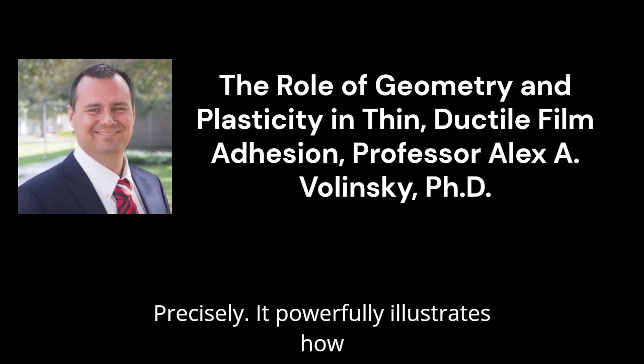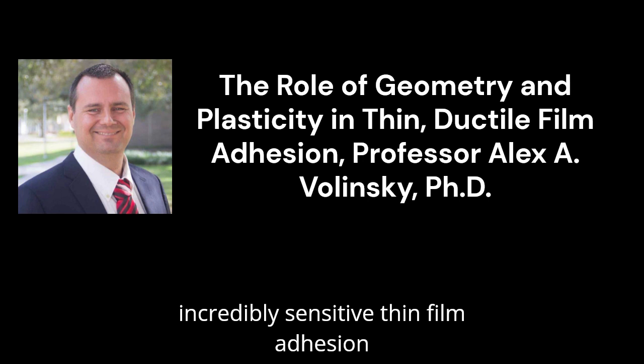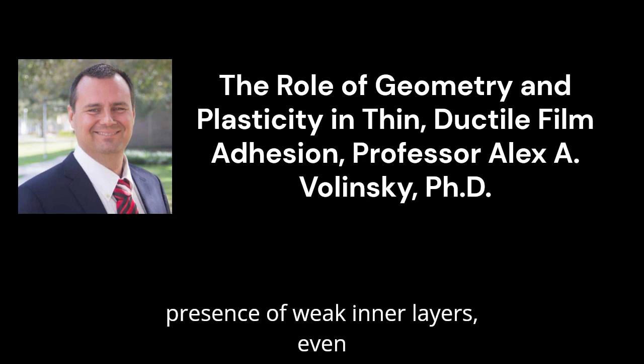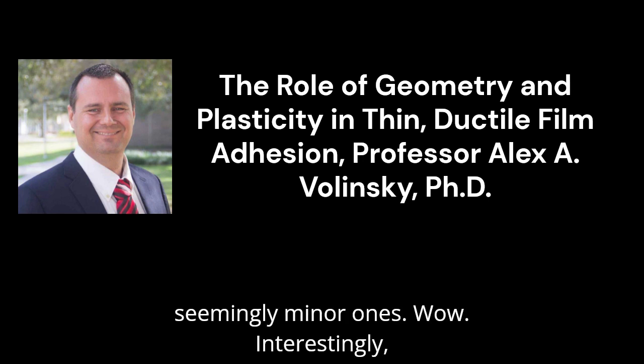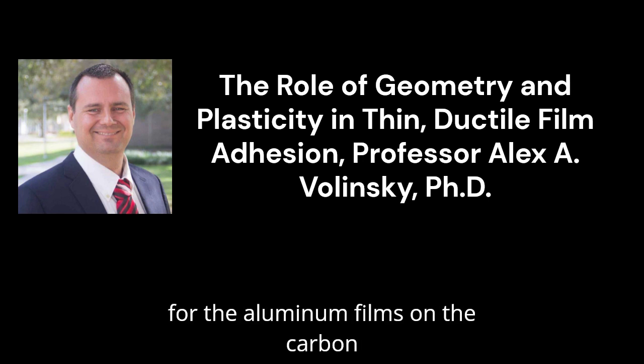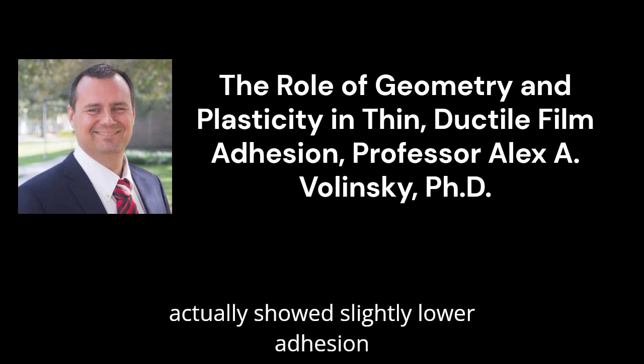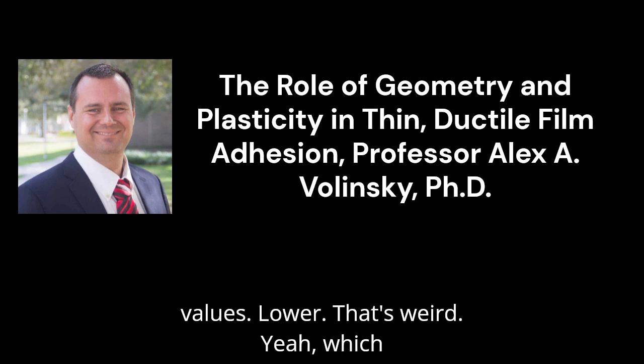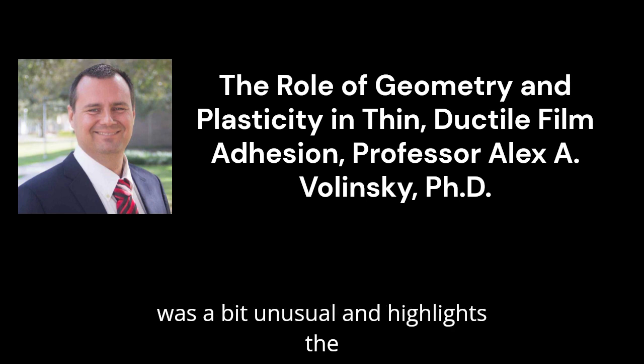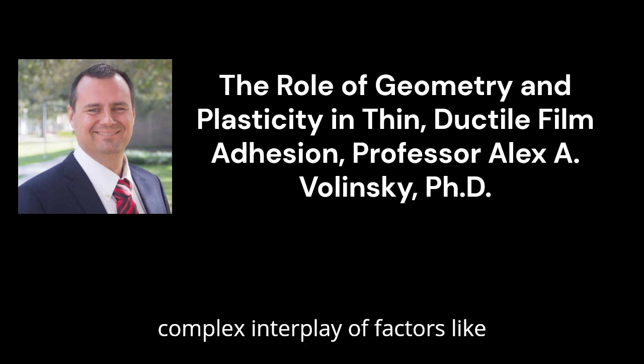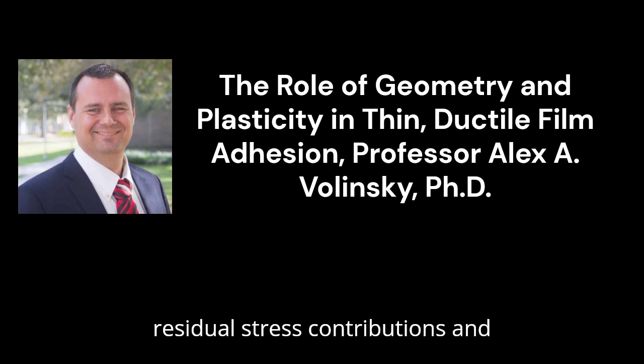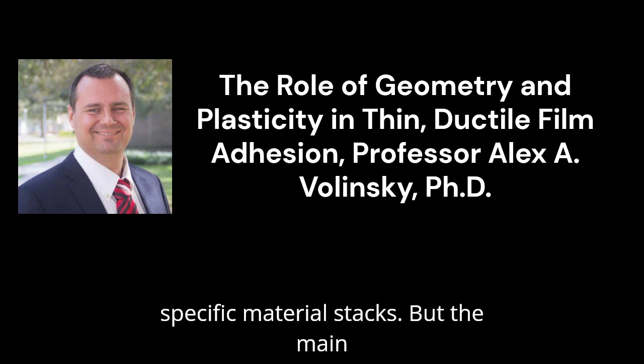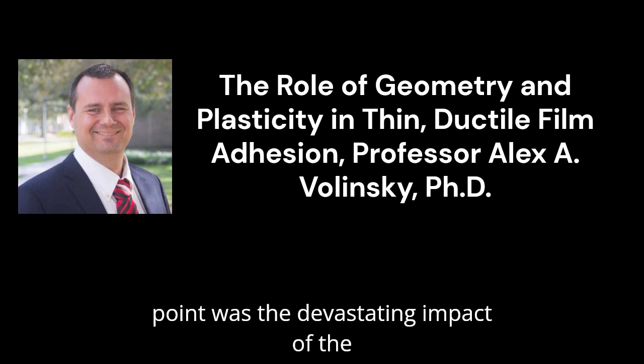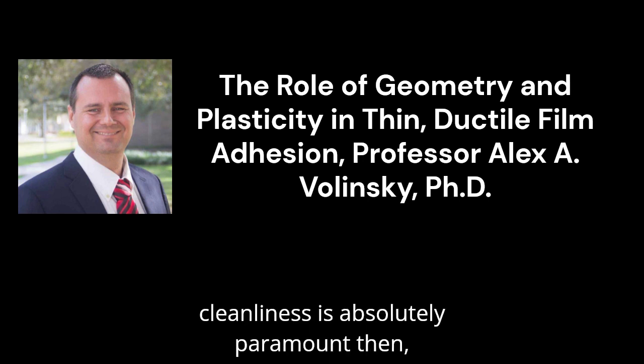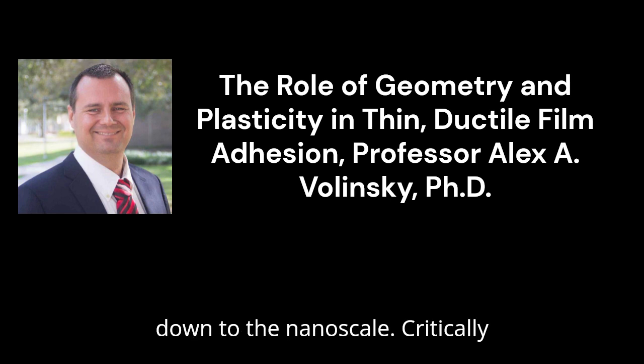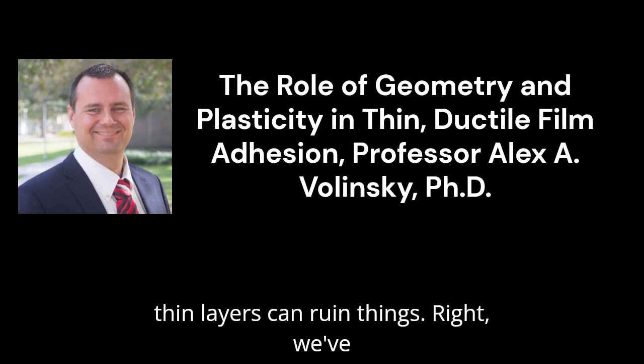Precisely. It powerfully illustrates how incredibly sensitive thin film adhesion can be to interface chemistry and the presence of weak interlayers, even seemingly minor ones. Wow. Interestingly, for the aluminum films on the carbon underlayer, the thicker aluminum films actually showed slightly lower adhesion values. Lower. That's weird. Yeah, which was a bit unusual and highlights the complex interplay of factors like residual stress contributions in specific material stacks. But the main point was the devastating impact of the contamination layer itself. So cleanliness is absolutely paramount then, down to the nanoscale. Critically important, yeah. Seems like even very thin layers can ruin things.